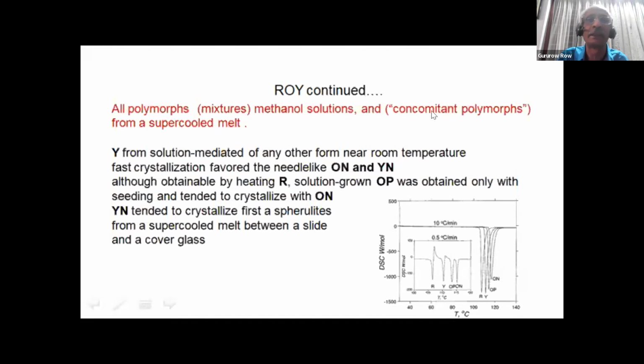And they come as concomitant polymorphs when they are crystallized from a supercooled melt. They come as concomitant polymorphs. We'll see what is concomitant polymorph in a minute from now. So why the yellow form from solution mediated of any other form near room temperature? Fast crystallization, if we do, it is favored to form needles. And again, a mixture of orange and yellow.